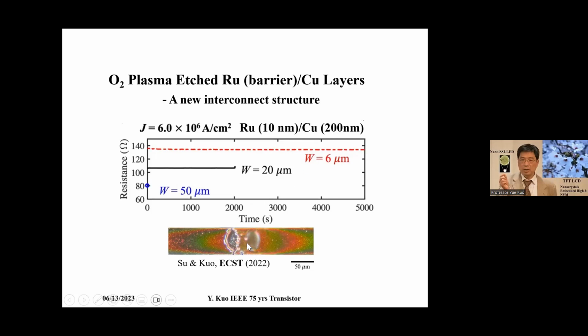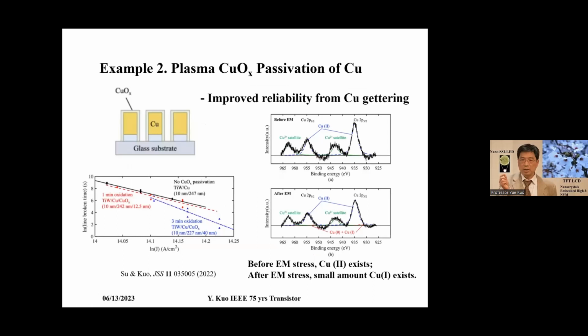Electromigration is similar to conventional interconnect metal. So since we can use oxygen to etch copper, another application we introduced recently is this: copper usually exposed to air will form native oxide, which is undesirable because it's porous, it's poor quality. However, if we use oxygen under controlled conditions, exposing copper to oxygen plasma, we form a thin oxide on the surface. Then the electromigration life is not deteriorated compared with pure copper.